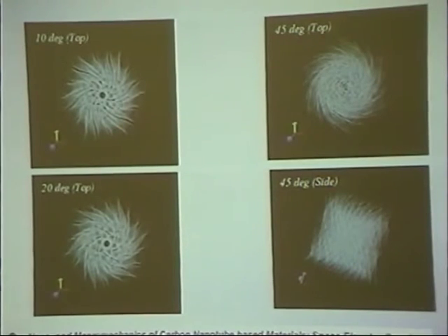Here I show you an example of a rope or bundle which is twisted by 10 degrees, and I'm seeing it from the top. You see this flower-like structure, and here is 20 degrees. But you see, this is 45 degrees. At 45 degrees, when I see it from the top, you see it starts to break. Where this strength is coming from is that when you twist it, for the tensile load it creates a compression force along this direction. If you continue to do that, that really breaks the nanotube. So 45 degrees is not a bad number actually. Twisting itself is going to increase my load transfer between them, and those are things that were not included in the previous model.